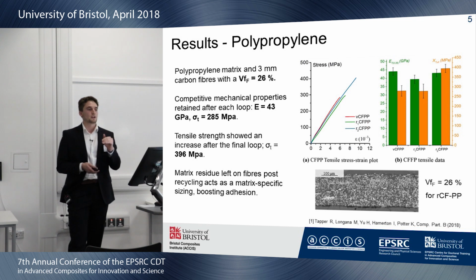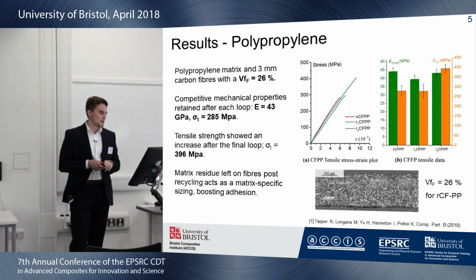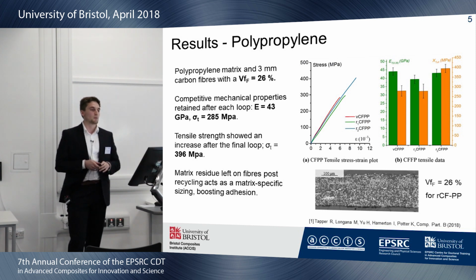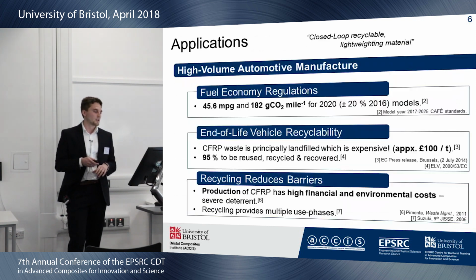And because the volume fraction remains the same, we think that this might be to do with matrix residue from the recycling process being left on the fibres, which acts as a kind of matrix-specific sizing, boosting that quite poor interfacial shear strength between polypropylene and carbon fibres. And we've got an increase of about 100 megapascals in strength on that final loop.